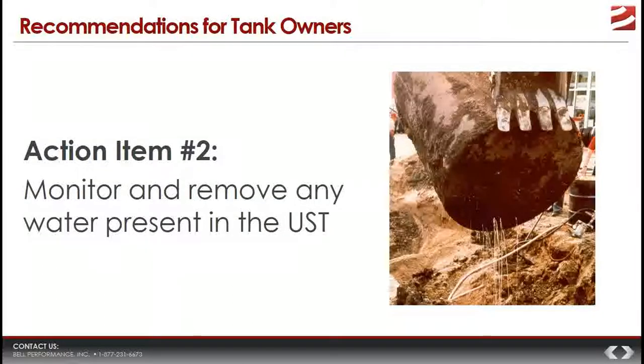Now, if you have a water layer next to a fuel layer, what's going to happen? Well, the law of osmosis, or whatever they called it in science class, dictates that something in high concentration will move to an area of low concentration. It will migrate. And so what happens in tanks is that the oxygen will diffuse, or move, from the fuel, high concentration, into the water, low concentration, to try and equalize the oxygen content. If this happens along tank surfaces, you will get localized pockets of oxygen, and that will speed up localized corrosion and metal loss where that oxygen is.